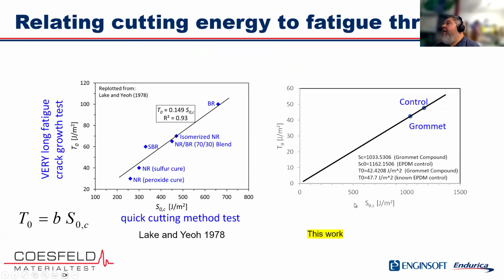And you can see here, this is a plot comparing the cutting energy that we measure with the blade to the inferred fatigue threshold. You'll notice they are different numbers. The reason for that is that the blade is not infinitely sharp, right? There's a finite radius of curvature at the blade tip, and so the difference between these reflects the sharpness of the blade. And so when we run this experiment, we run the control material so we can calibrate for the sharpness of the blade.